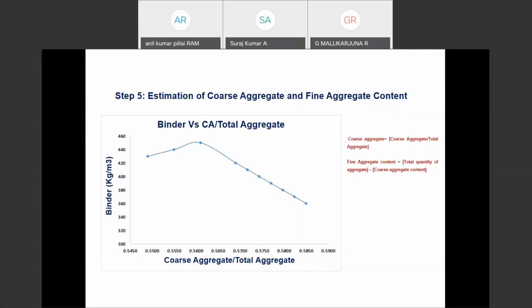And here this is the estimation of your coarse aggregate to total aggregate ratio. Here the coarse aggregate is nothing but coarse aggregate by total aggregate. Once you know the total aggregate ratio, after total aggregate ratio, the total quantity minus coarse aggregate, you are going to get the fine aggregate content there.